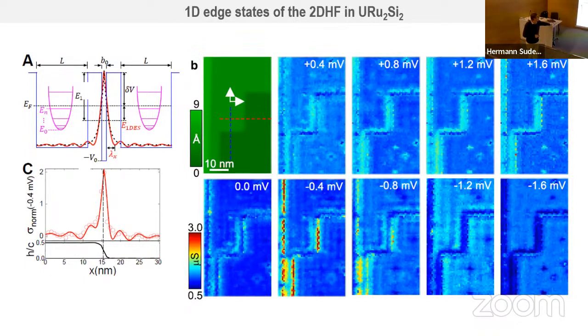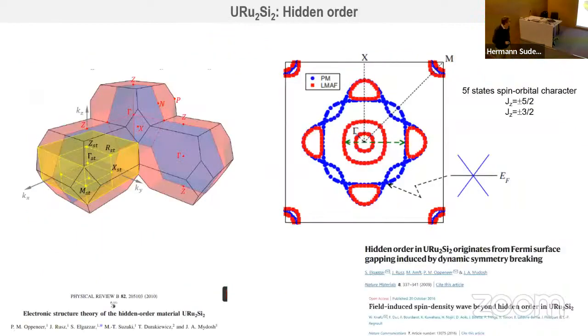Now, what is very peculiar here is that this is a system which has fourfold symmetry. Now here, this has not fourfold symmetry. So this is located here and here, but not here. So this is something which is very puzzling indeed, because if the electronic structure is fourfold symmetric, it should be also fourfold symmetric. Now, of course, this may be related to this hidden order.